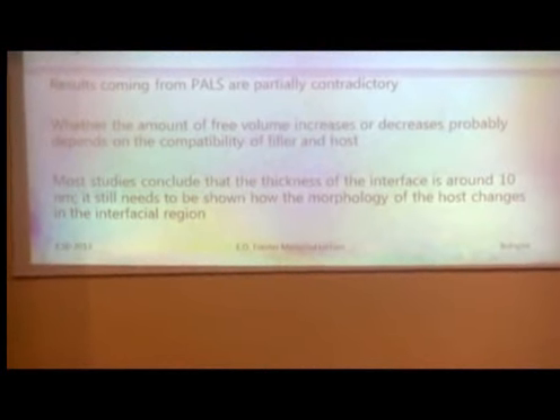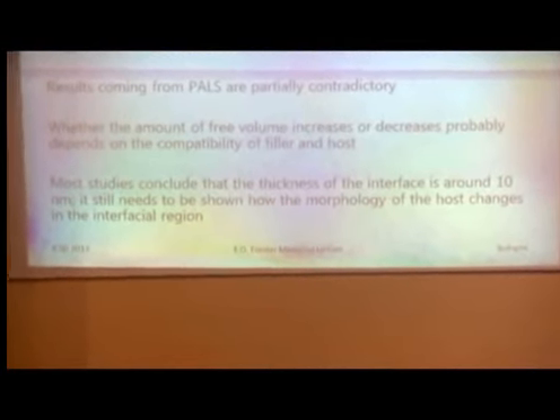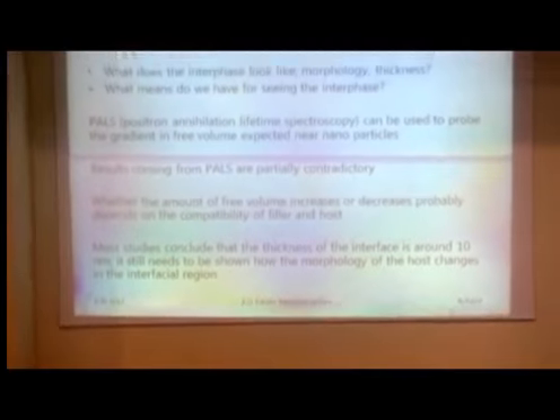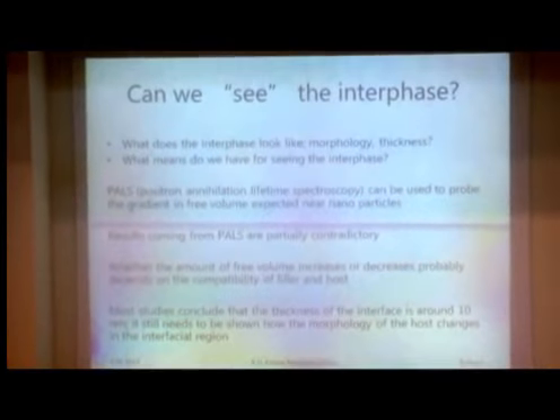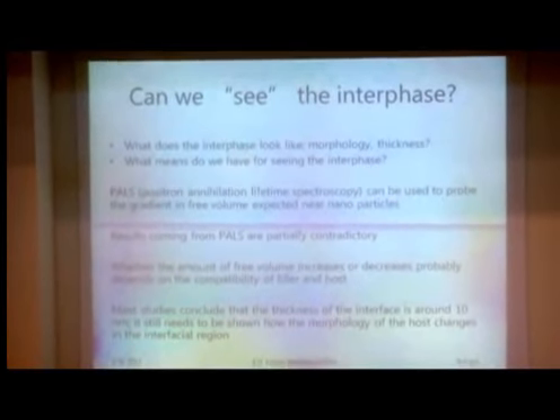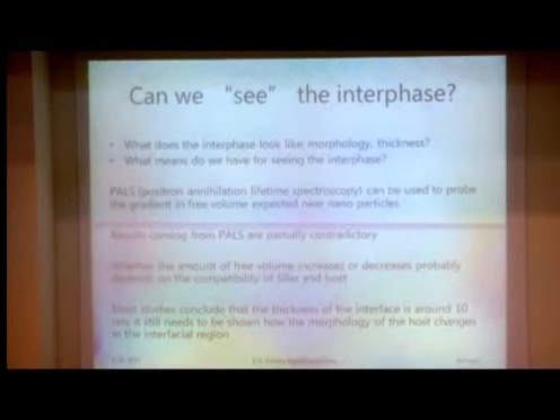In the end, most studies, but nobody has ever seen the interface yet, conclude that the thickness of the interface is around 10 nanometers. But again, it's by far not enough to explain what we see. So there's a lot of work to be done here.